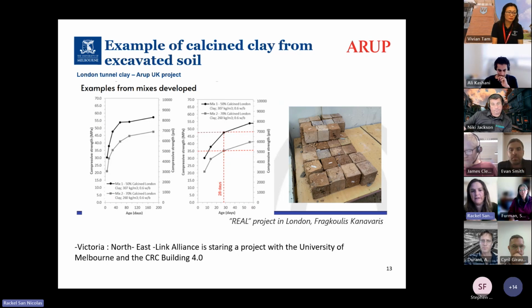What is interesting is, depending on the target and the application, there is a lot of potential for this material, and you can substitute up to 70% of the cement system and still have an okay or good kind of application. So that's really a project, and what I like is that through the tunneling, they had this material, they wanted to make use of it instead of just putting it in storage, and that's really where the story is from and what we can do with this kind of technology.